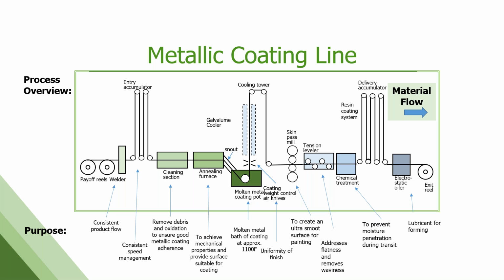It comes through a snout into a giant bath of molten metal, about 1100 degrees Fahrenheit, very high temperatures. The strip moves through that bath, the metallic coating gets applied, and it goes through a set of air knives. These air knives are spraying air onto the strip to control how much of that coating stays on the strip. We measure that by thickness and by weight. It goes through a cooling tower to get cooled down. You've got to cool it at a very specified rate or that coating doesn't stick.